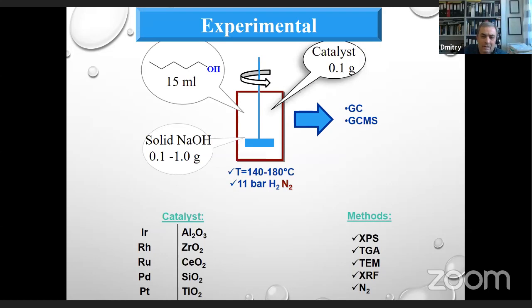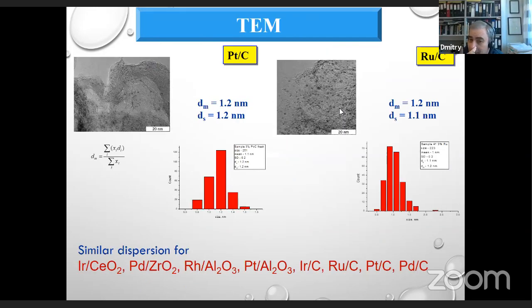A few words about the experimental part, just for you to have an idea about how experiments were done. So this is the reactant. It was put in an autoclave in addition to solid sodium hydroxide. Experiments were done in this range of temperatures, either under hydrogen or in an inert atmosphere under nitrogen. Different types of catalysts were tested, different noble metals, iridium, rhodium, ruthenium, palladium, platinum, on different types of supports with different nature, more acidic, less acidic, amphoteric, almost inert like silica. Here are the methods for catalyst characterization and for characterization of reaction products. The catalysts were prepared in Novosibirsk, and they had very high dispersion.